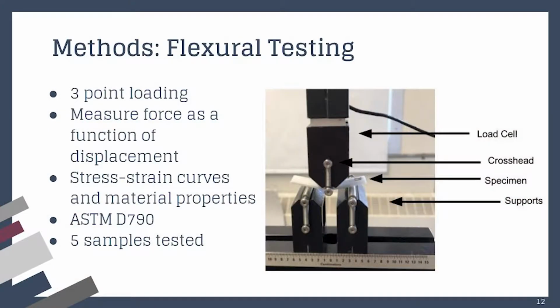So the second test we conducted on our specimens was flexural testing, which tests for stiffness of a material. So we used a 3-point loading system, and so the bar is placed across two supports, and a load cell is brought down on it, and so the force is placed on it, and we graph it as a function of displacement. We collected stress-strain curves as our data, and we followed the ASTM D790, and 5 samples were tested for composition.